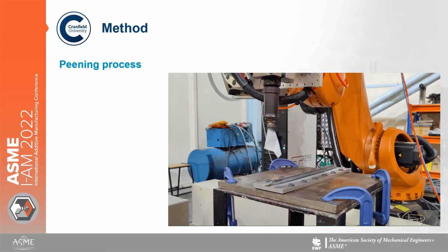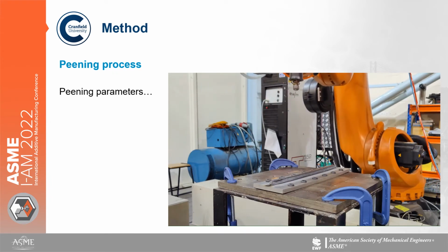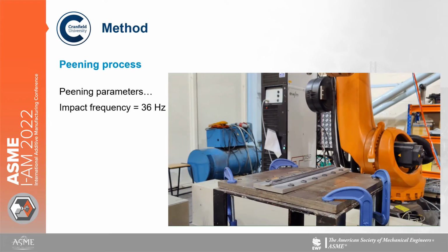So that's our peening process, and the peening parameters we used was an impact frequency of 36 Hz, and that's the frequency that the peening tool is impacting the top of the deposited layers. And the peening tool used a load of 30 kilograms, which is the load sitting above the peening tool.